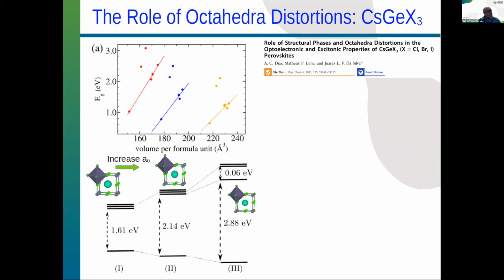In the first figure, with the Roman label 1, we have the ideal structure. It has a band gap of 1.6. Keep in mind that this band gap is a DFT band gap. We have some small error compared to experiment, but what we have to look at here is the changes. So you have the ideal structure, no distortion, the perfect one, with a band gap of 1.6. Now we go to the third figure, the third Roman numeral here, which has a band gap of 2.8. And this structure has a distortion of the octahedron. It's a cubic lattice, but it's a Jahn-Teller distortion. The band gap changed from 1.6 to 2.8.